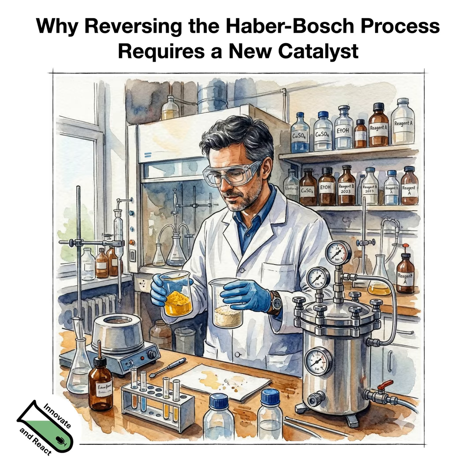If you use the very same catalyst for the equilibrium limited ammonia synthesis reaction, you will not reach high ammonia partial pressure, right? The limitation is below 20%, maybe around 20%, and you will not get more than that at the conditions where a typical ammonia synthesis plant is run. And that partial pressure is typically not enough to nitride the Haber-Bosch catalyst. So the same catalyst forms an iron nitride in ammonia decomposition and is iron metal in ammonia synthesis because of the difference in the partial pressure of the ammonia in particular.